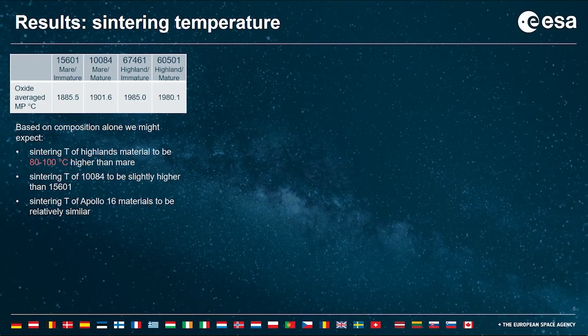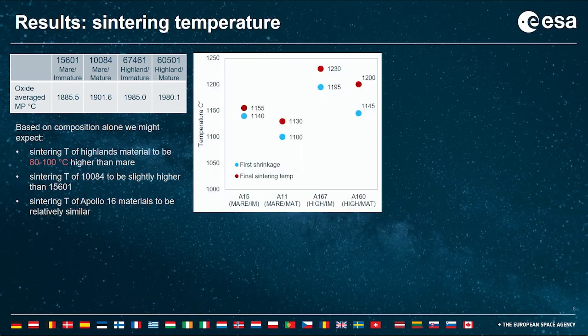We also might expect that the Apollo 11 sample would sinter at a slightly higher temperature than Apollo 15, and the Apollo 16s should be relatively similar because they came from the same landing site. So this graph just shows the final sintering temperature in red, and then also the first shrinkage temperature in blue. So that's where the material first shrunk away from the walls, and it was removable as a poorly sintered pellet.